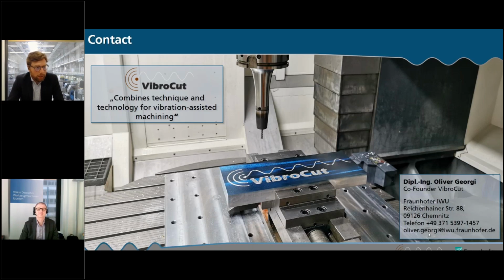Yeah, that's a good question. In conventional machining, we have the straight feed lines which build up a spiral on the surface. And when you now use the vibration assistance, then the path of the cutting edge is changed. So you have an overlaid sinus curve. And with the parameters, we can design the surface, and overall the topology of the surface looks different than from the conventional process, but you can reach the conventional roughness. So that's also a point for the industrial integration of the processes. When we have roughing processes, that's no problem because there is a finishing operation afterwards. But when we go to finishing operations, then especially in serious production, you have to have a look at the surface, and there is a point to prove the surface.